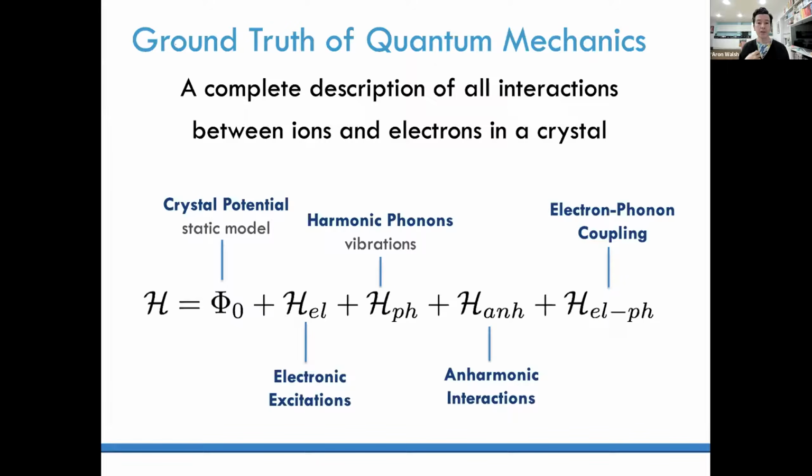But increasingly for materials research, we're driven in a direction where anharmonicity is becoming increasingly important. If you're interested in thermoelectrics, it's all about tuning thermal conductivity. Thermal conductivity is only defined when you have these anharmonic terms. So you also have to include some description of anharmonicity. And then you have coupling between vibrations and the electronic states, so you have electron-phonon coupling to incorporate as well.